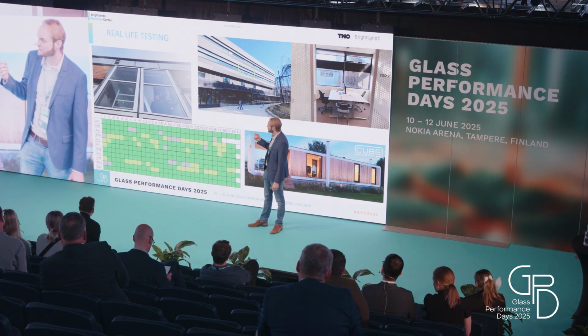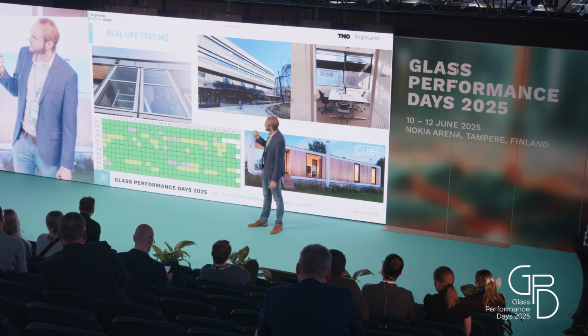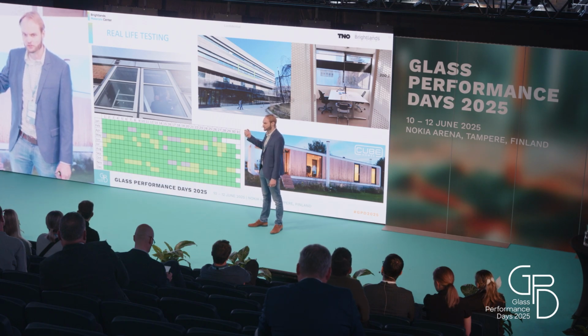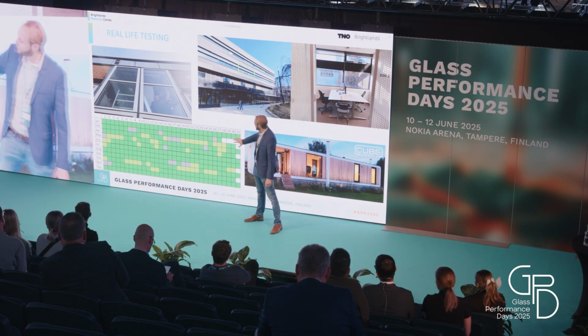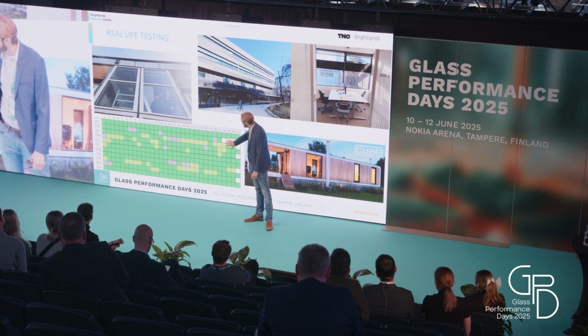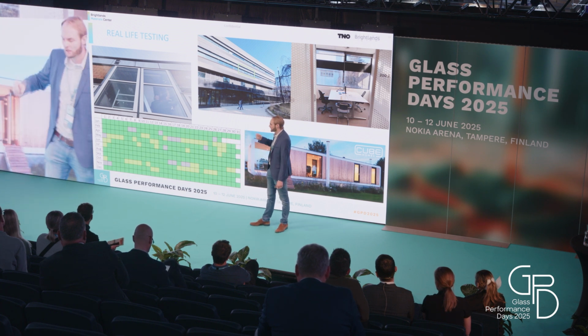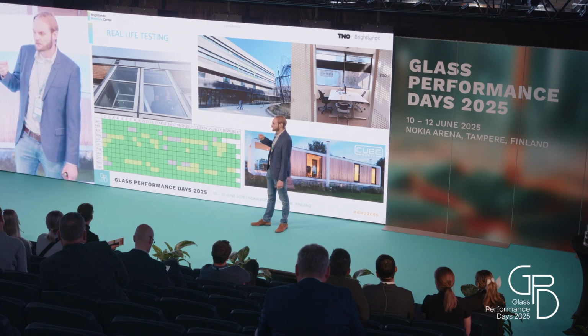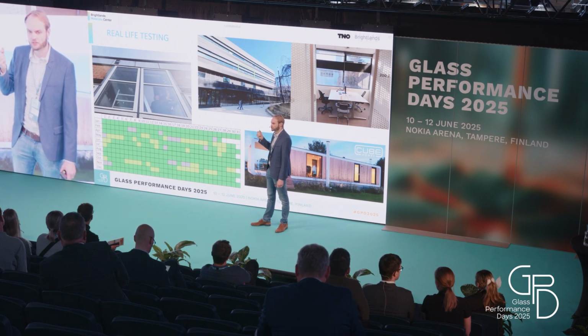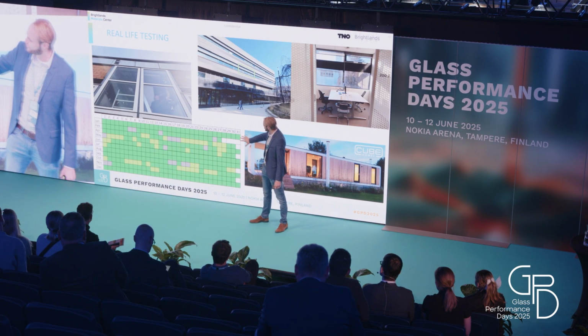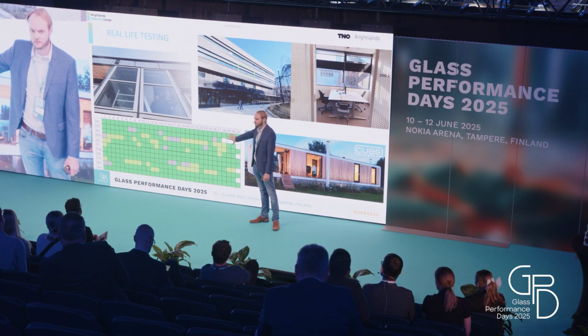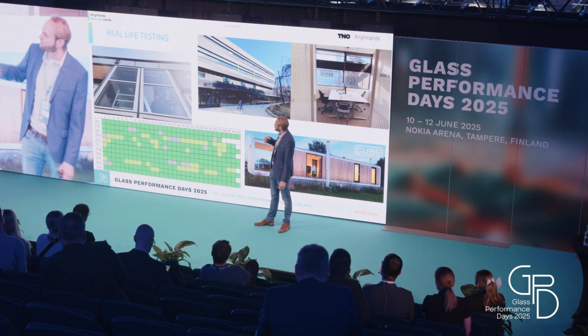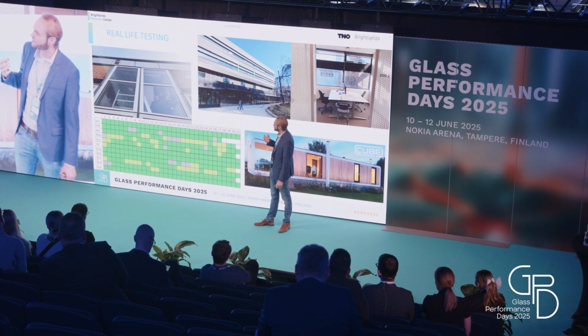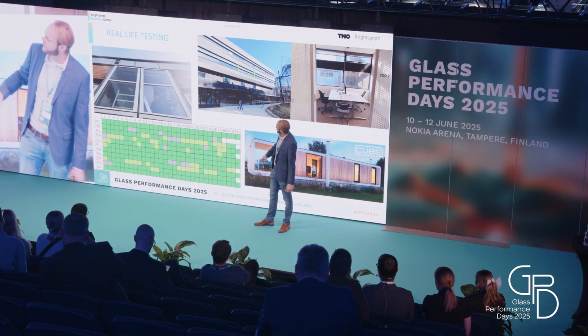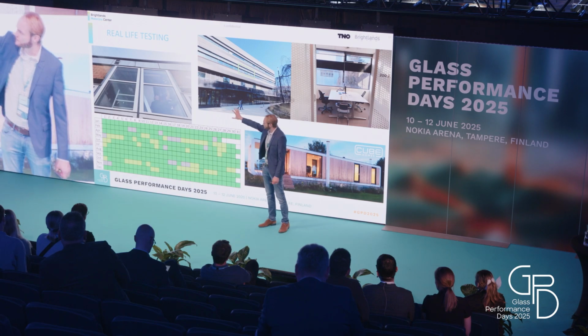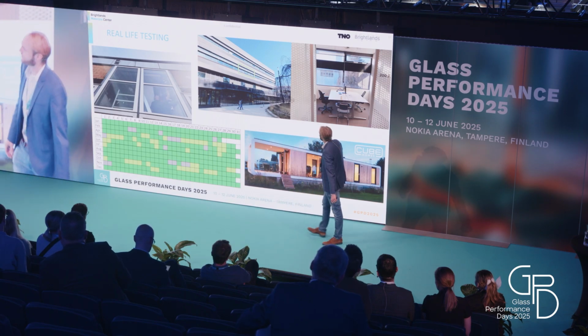And what we saw there is that the glass temperature can actually be significantly higher than the outside temperature, which means that in the beginning, especially in spring and in autumn, there were some days where the glass temperature was already significantly hotter than the outside temperature, and the material transitioned, even though we didn't want that. So we used this monitoring to optimize our material, so that it's now perfectly optimized for the climate region in the Netherlands and in the Benelux. And now the second optimized version we installed again, to monitor it and look at the performance.